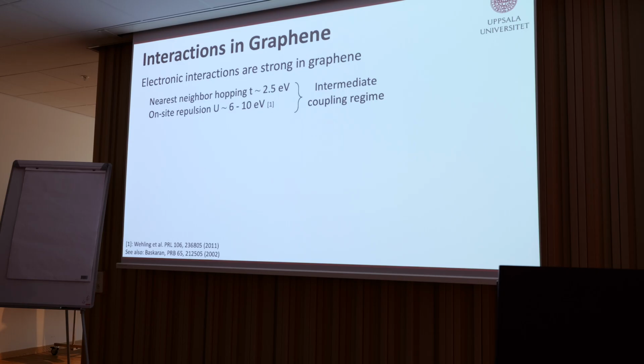Well, we choose to go back to thinking about what the physics is in graphene. In graphene, you have nearest neighbor hopping around 2.5 eV, and there is an on-site repulsion that's actually rather large, around 6 to 10 eV. So if you compare U over t, you are not in a weak coupling regime. You're in some intermediate coupling regime just for single-layer graphene. Now, in single-layer graphene, you don't see much interaction physics because you don't have any density of states. But here I have a system where I should have similar interactions, and I have a lot of density of states at zero energy because of the flat band.